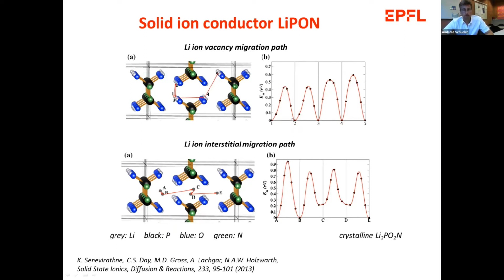This energy barrier would then be seen here as a bump in this energy diagram. An alternative migration path is the interstitial migration path, where the lithium ions migrate here in between the lattice sites. And there are also energy barriers involved here. In this case, the energy barriers are a little bit higher, and the dominating migration path is most probably the vacancy migration path.